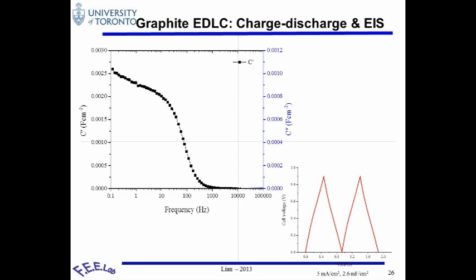The more important thing is the blue curve here, which is the imaginary capacitance. The peak at the imaginary here corresponds to a 45 degree in the impedance. Physically, this means that at the higher end, it's a resistor-dominating behavior, and at the lower end, it's capacitive behavior.